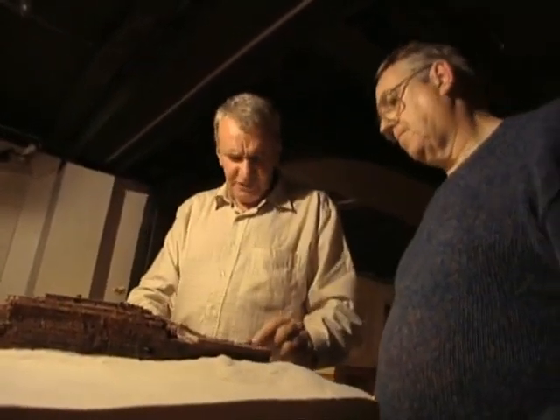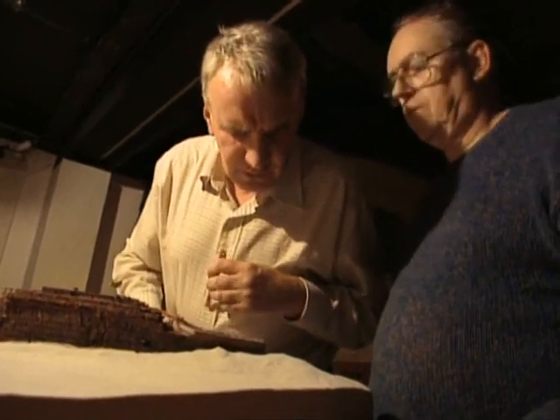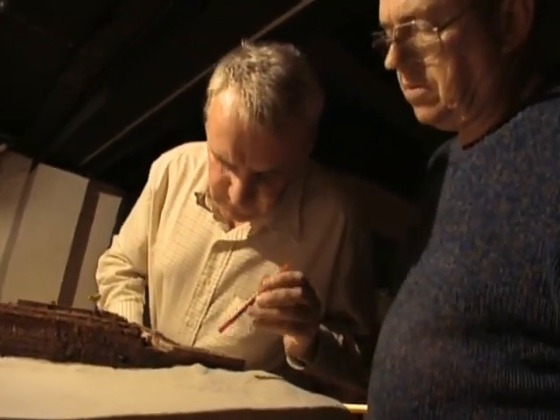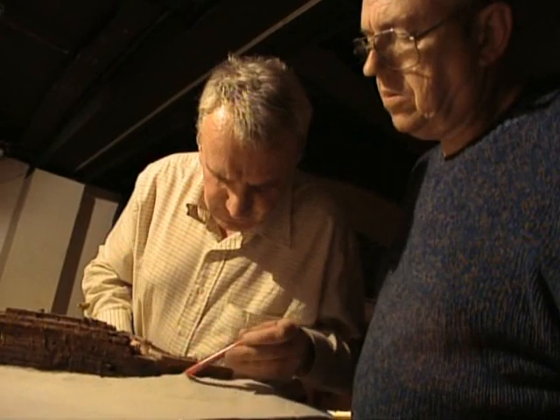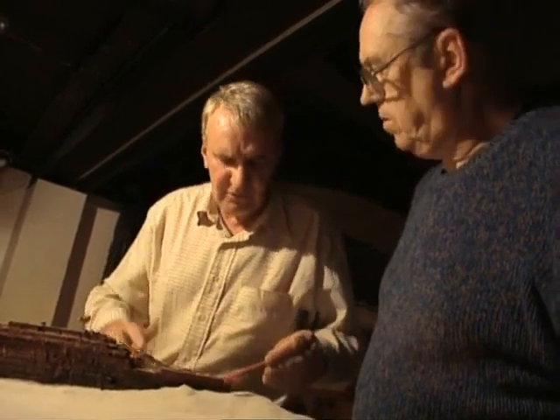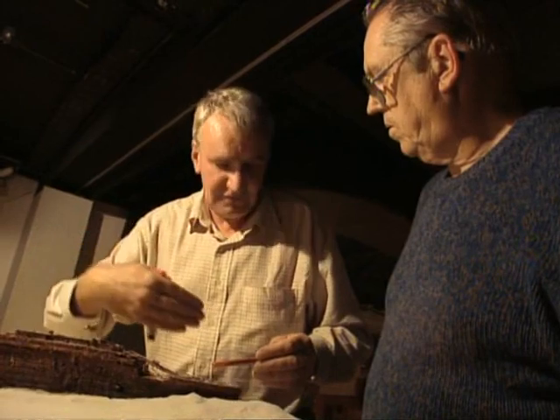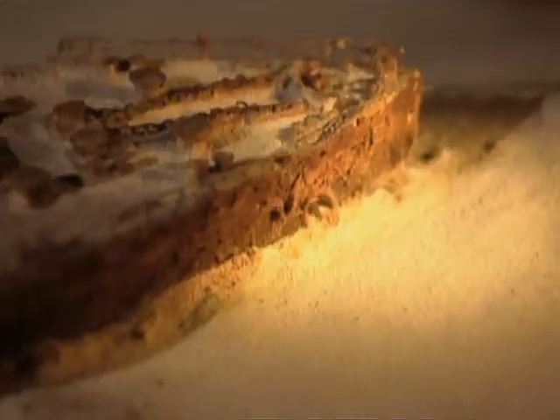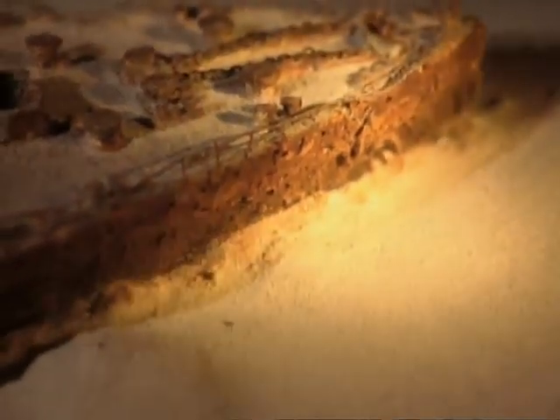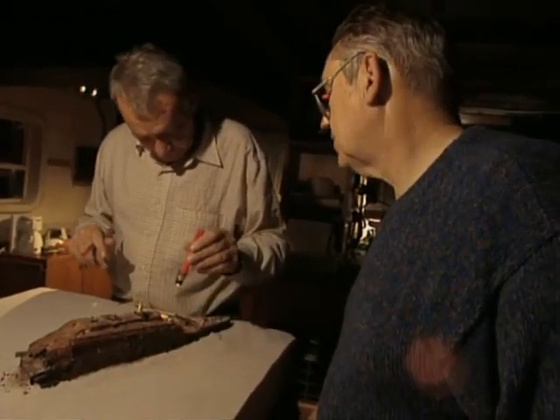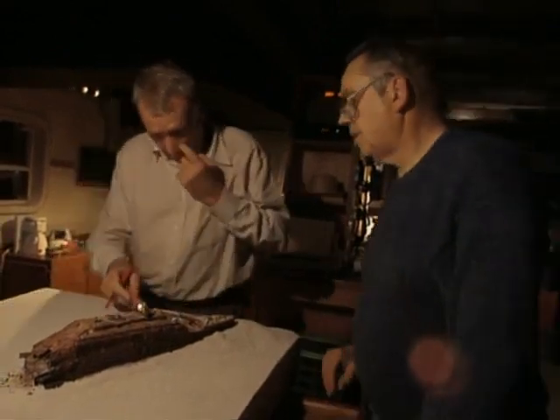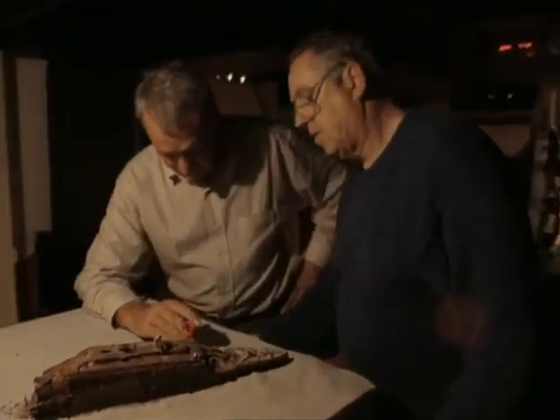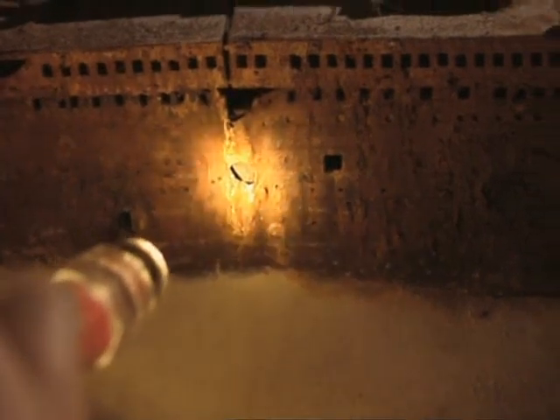Livingstone believes that the wreck site holds clues to how the bow arrived in its final position. On the starboard side, there is this big wave, almost a bow wave of silt, where the ship was pushing in. And the bottom of the anchor is just about on the silt. I see. Another clue to the bow's impact is found on the port side. Over the top of the bridge, and to Livingstone's surprise, there's a giant bend in the hull. At the big radius bend.